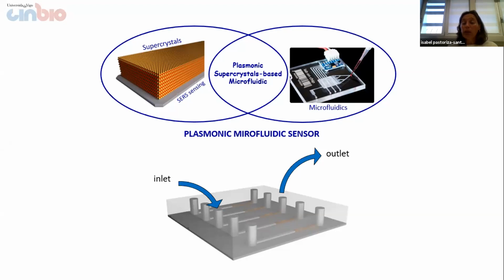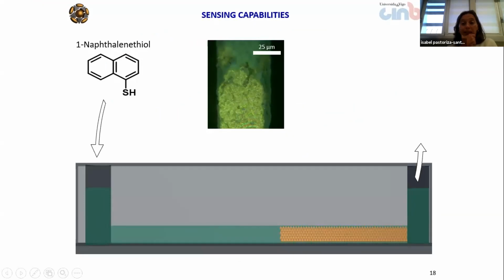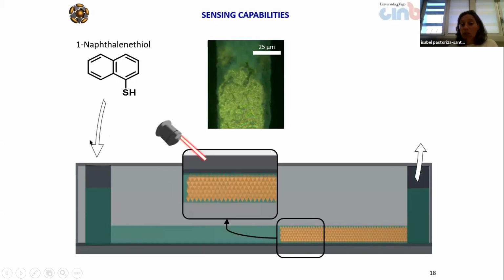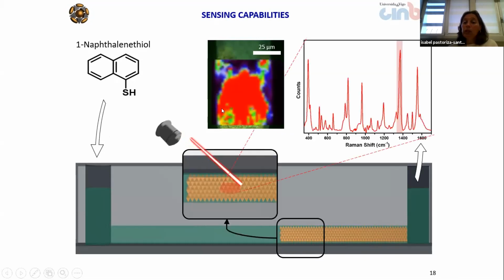Since we are interested in the detection in flow, we have a punch at the end of the channel, an outlet. The next characterization that we performed was to check the sensing capabilities. We use naphthalene thiol as a model molecule. We inject it with a pump at a certain concentration, and first we check that the distribution of the molecule in the supercrystals is rather homogeneous.